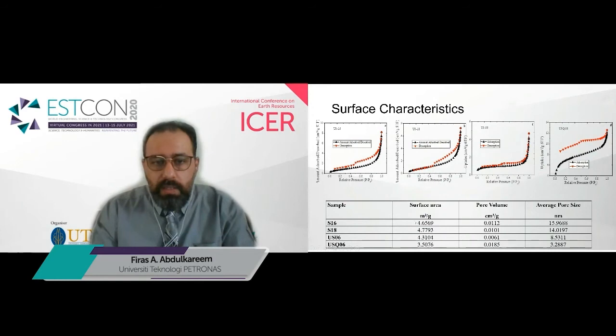And as we can see here, the surface area is more or less identical across the 4 shale types, even though their total organic content was totally different. However, the pore volume of S16 is the highest, along with USQ06, among the others. Likewise, the pore size is the highest for S16 compared to the others, way higher compared to US06 and USQ06, even though their TOCs were much higher compared to S16.